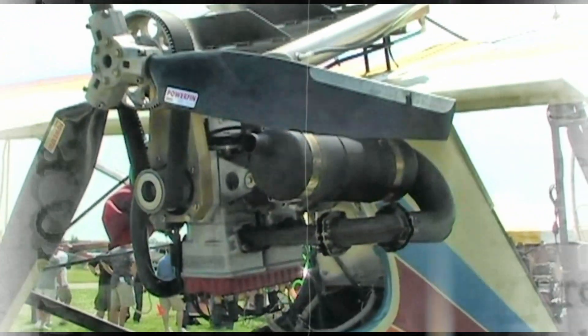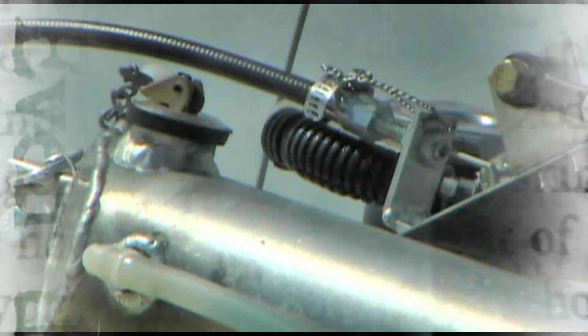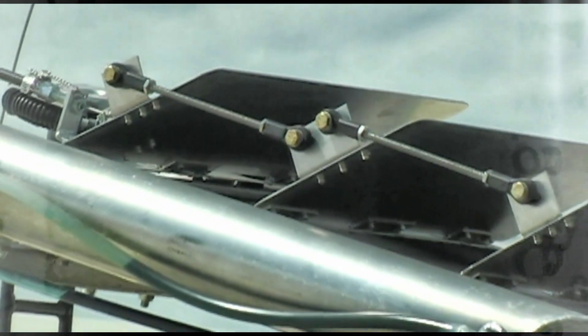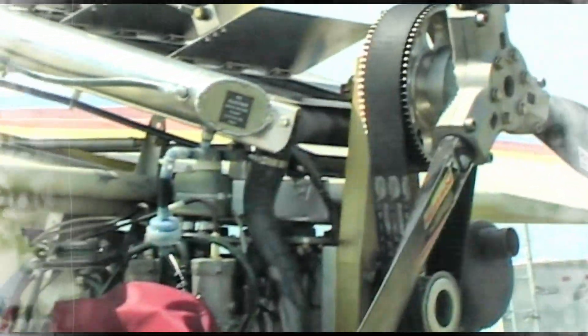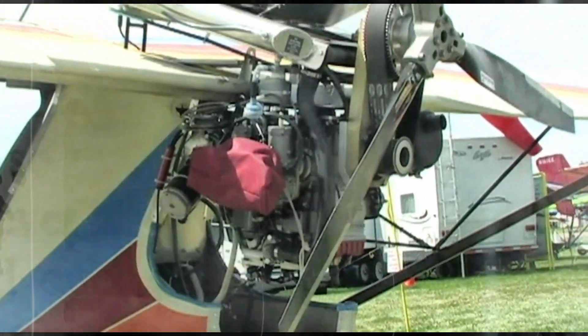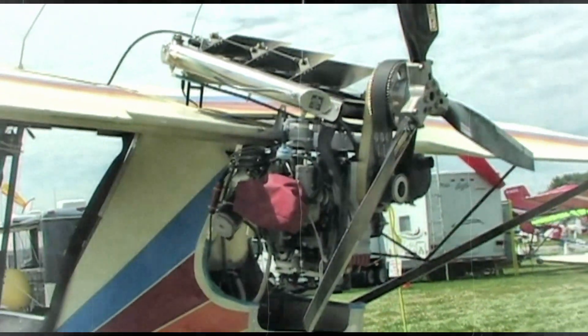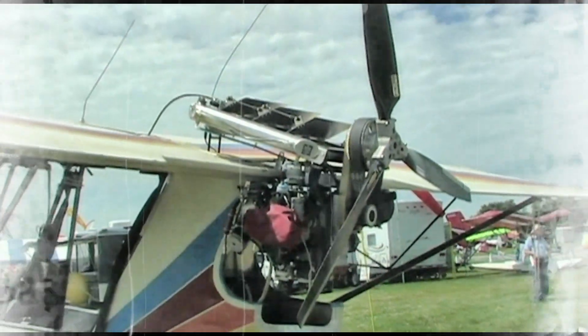The cracks identified vary in size and origin — some resulted from fatigue, whereas others were caused by material delamination. A review of the National Transportation Safety Board Aviation Accident Database revealed four other Quad City Challenger 2 accidents involving in-flight wing attachment bracket failures that led to in-flight wing separations. Three of these accidents were fatal. In the non-fatal accident, the pilot successfully deployed a ballistic parachute and was not injured.